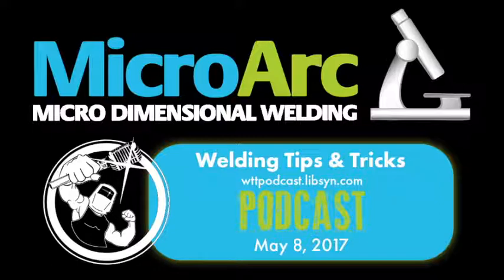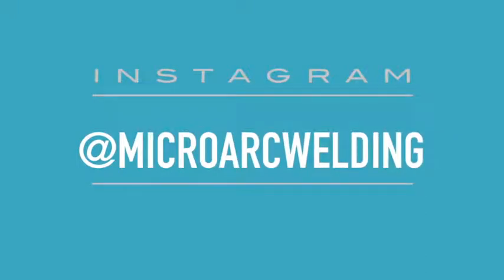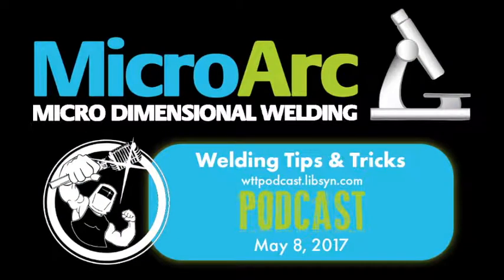Right. There's preheat, then there's post heat. Sometimes we'll put it back on. We have these little digital heaters, and sometimes I've welded something while it's on the heater, because it's so susceptible to cooling. When you're doing micro welding on a big block of steel, it's not really staying hot. True, because the heat that you're generating isn't overcoming the heat that's normally being lost. So we might weld it for a little bit, put it back on the heat, weld it a little more, put it back on the heat.